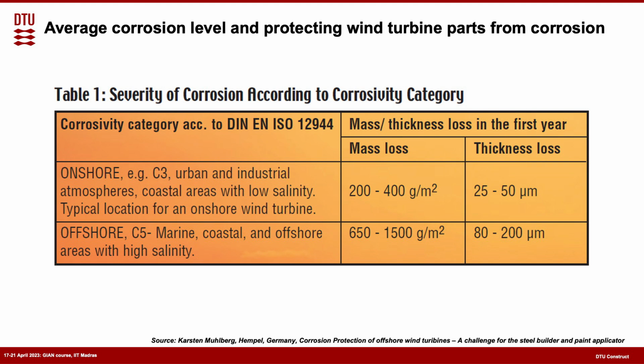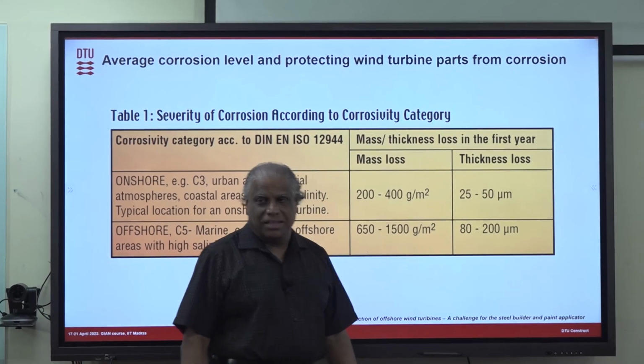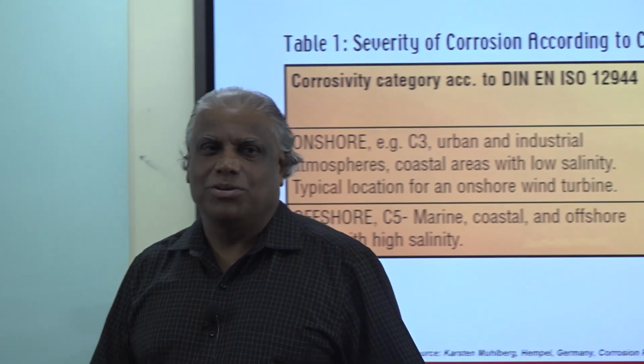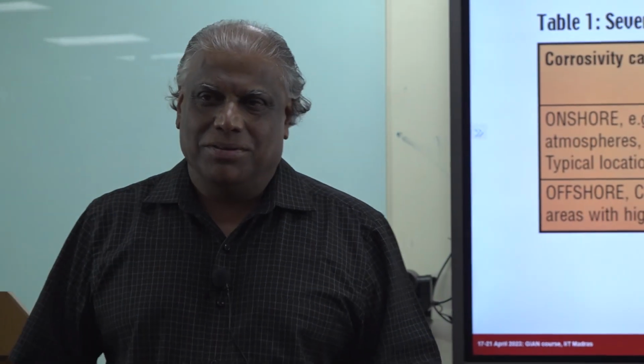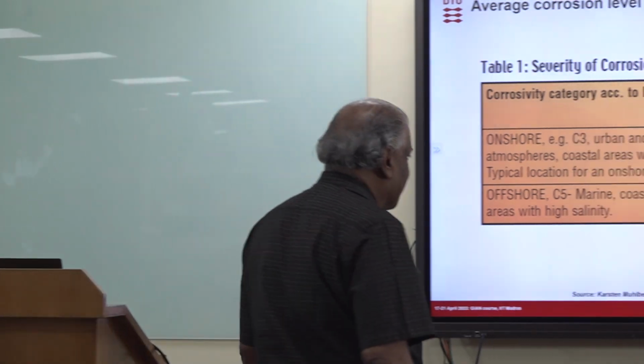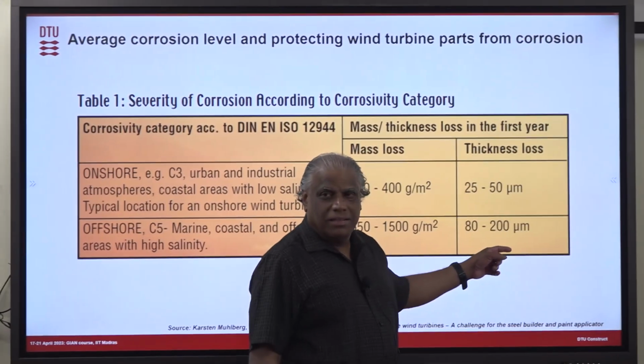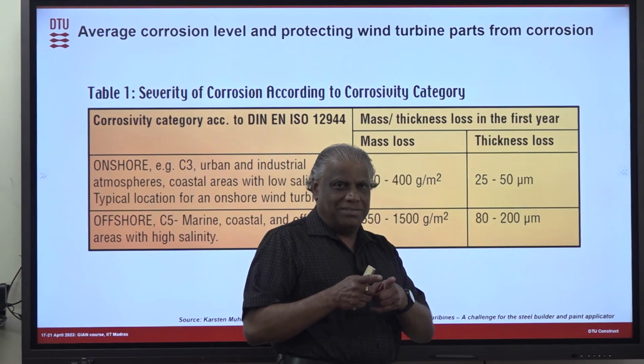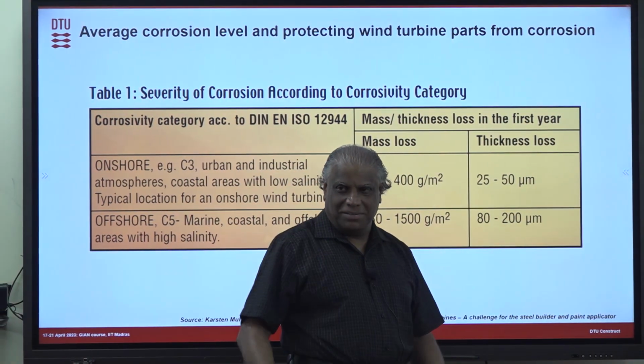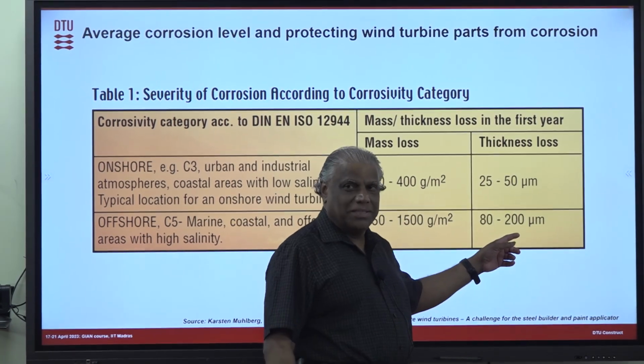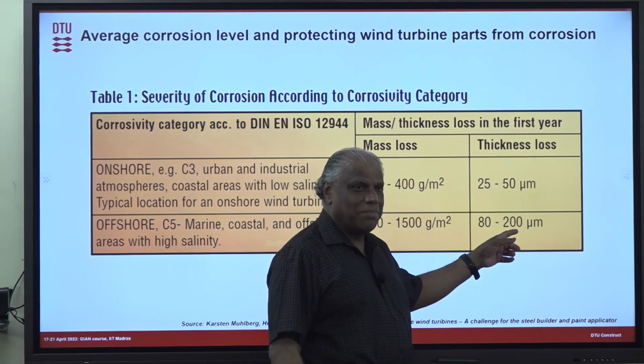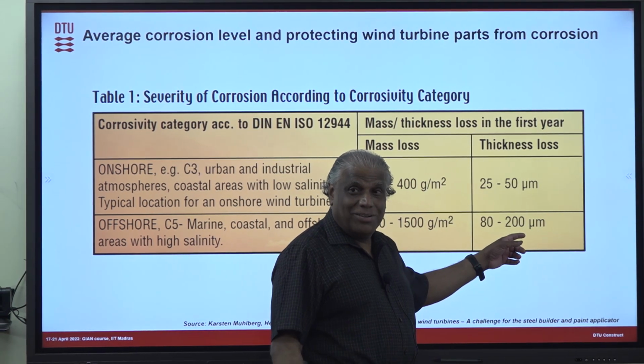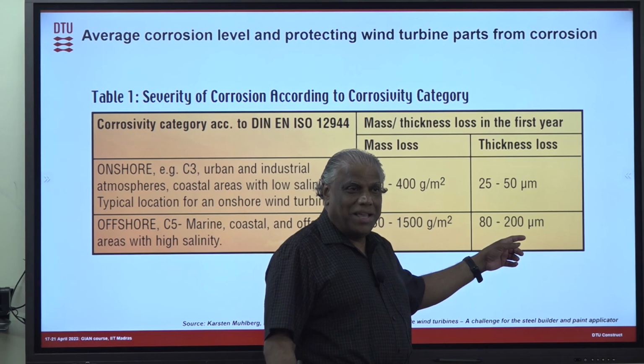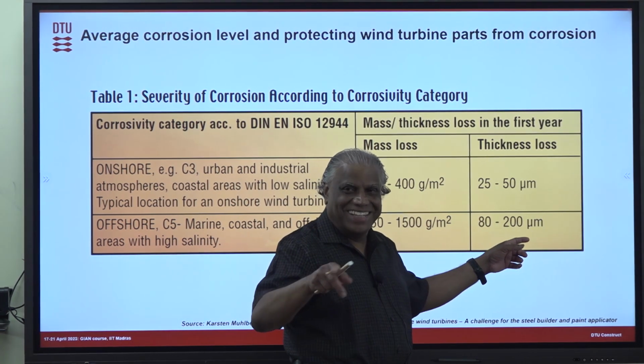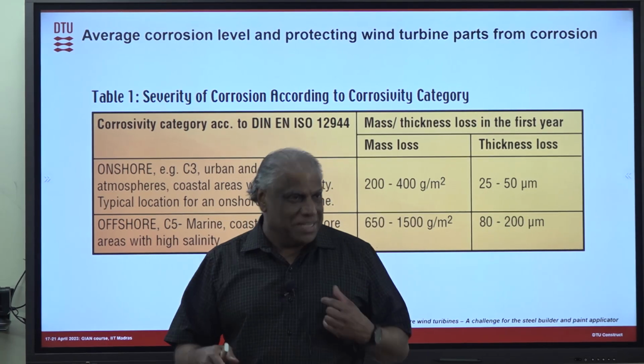And if it is offshore, which is C5 condition, you get around 4 times of that, around 200 micrometer. That's the kind of corrosion level you are expecting, which also means that you need to have this level of protection. Remember that 200 micrometer itself is not a big thing. Think about you have a very thick steel tube for the tower. But the problem is that this 200 micrometer is an average corrosion level. Think that in one place it is 2 millimeter, another place it is only a few micrometer, like a pitting sort of thing.